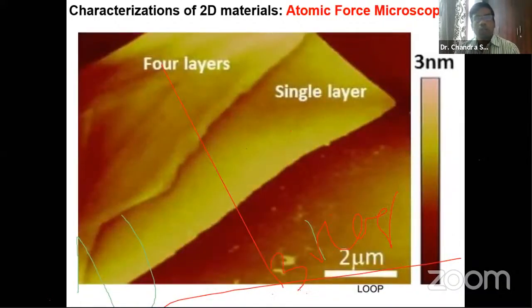So this is the atomic force microscopy of some material which was collected by atomic force microscopy. The image looks like this. So this is one graphene. Suppose you are telling single layer graphene. If you make the height profile analysis, the thickness will be around 0.34 nanometer. If it is 4 layers, it is multiplied by 4, like 0.3 into 4. If you are getting the thickness in that range, you can tell it is 4 layers. Similarly, if you are getting bi-layer or tri-layer, you can calculate how many layers are present in your sample.